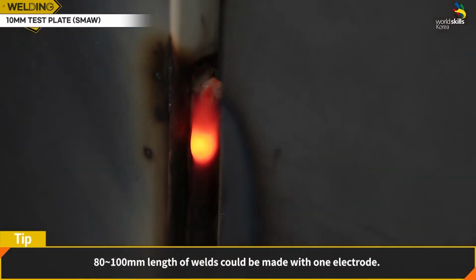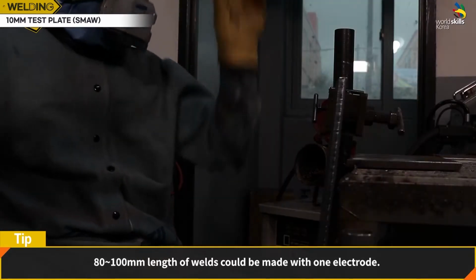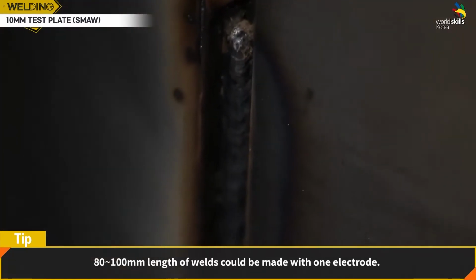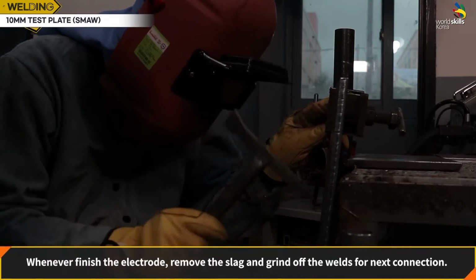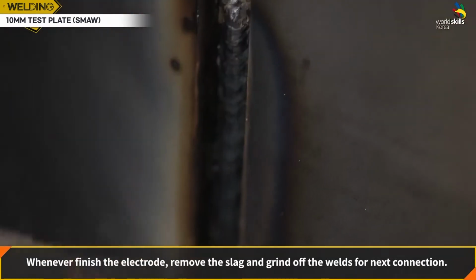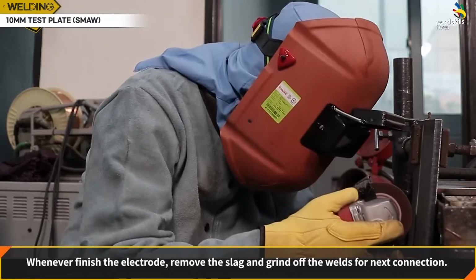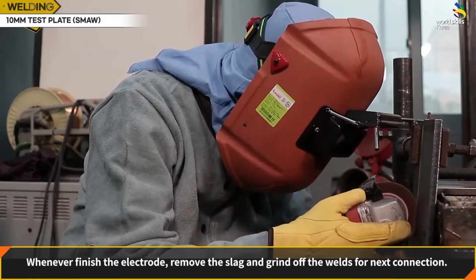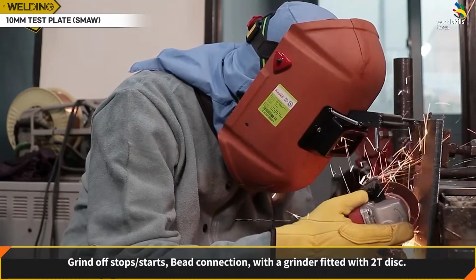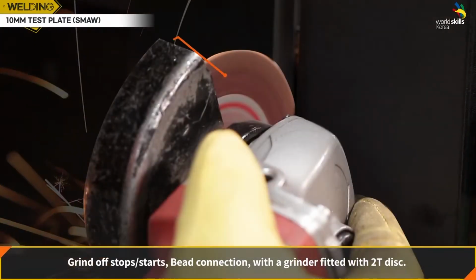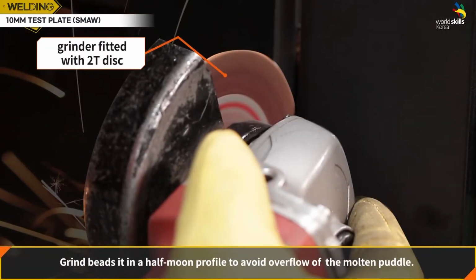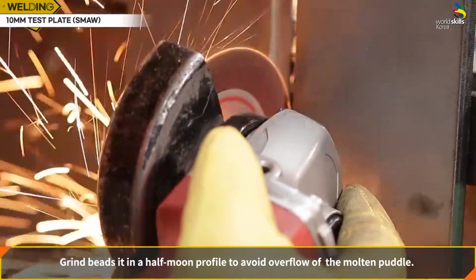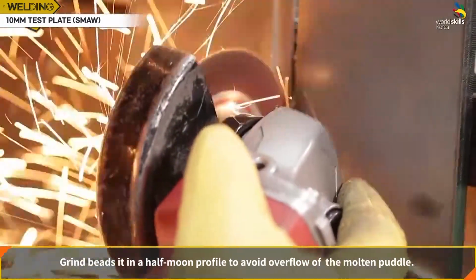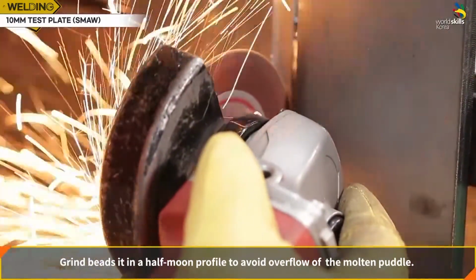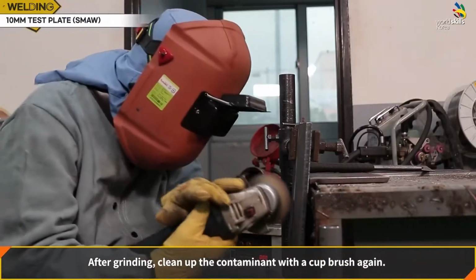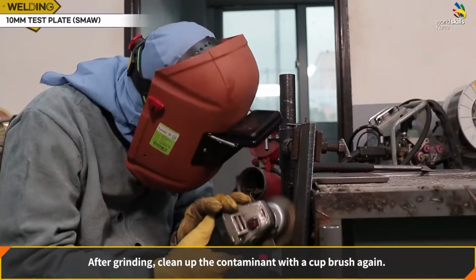80 to 100 millimeter length of welds could be made with one electrode. Whenever you finish an electrode, remove the slag and grind off the welds for the next connection. Grind off stops, starts, and bead connections with a grinder fitted with a 2T disc. Grind beads in a half-moon profile to avoid overflow of the molten puddle. After grinding, clean up the contaminant with a cup brush again.